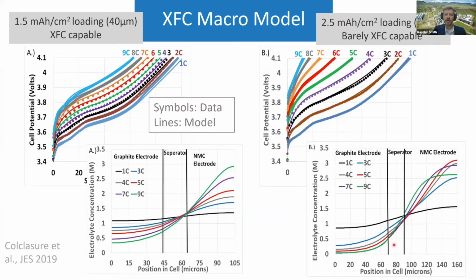And so you very quickly saturate the surface of the graphite particles and then start with the onset of lithium plating. And this is a key thing that any reduced order model that's interacting with a control strategy for fast charge has to be able to predict: the electrolyte transport limitation. And it's highly nonlinear. Some of the work that I did for my PhD thesis was to develop reduced order models that were very linearized. And I think those are not suitable for this particular condition. So that's something that I encourage all of you control-oriented modelers to make sure that your model matches up closely with the full order model under that condition.